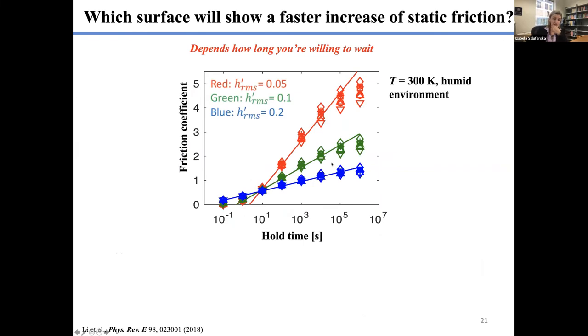So that allows us to answer such questions as which contact will age faster, the rough or the smooth one. And so this is friction coefficient, could be friction force. Either way, friction coefficient is a function of hold time. So we're basically holding the tip. We consider different roughness parameters for the surface. This is the one that has a largest effect. The surface, the blue one, is the roughest. The red one is the smoothest. And so if you put the contact together, the question is which one is going to age faster? And the answer is it depends on how long you are willing to wait, right?